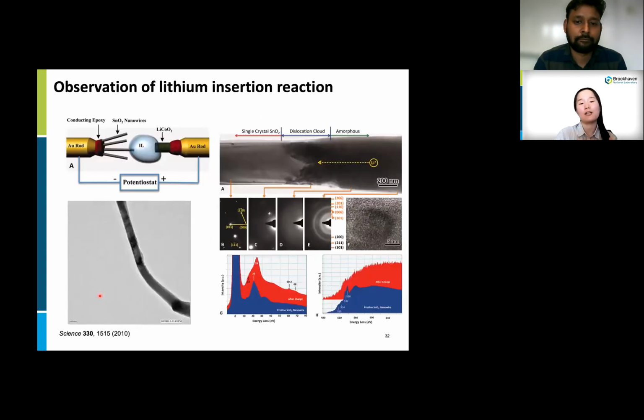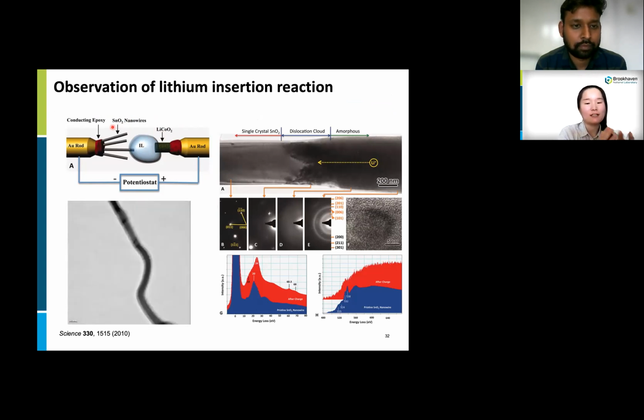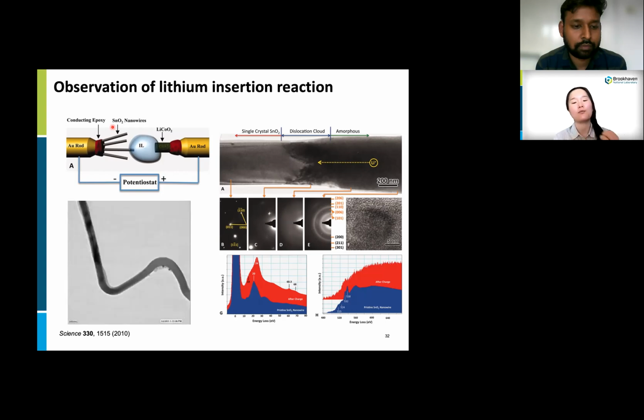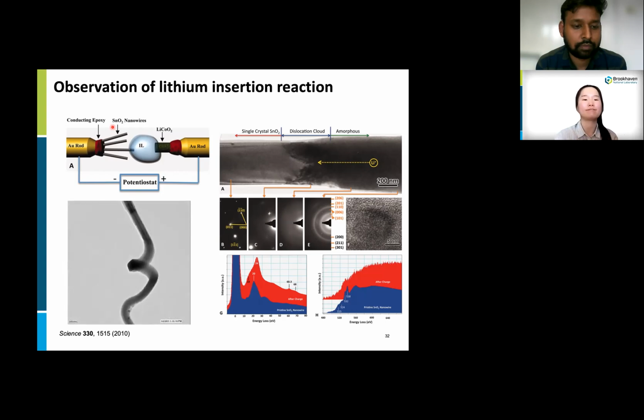An open cell configuration shown here has successfully mimicked battery systems inside transmission electron microscopes. Lithium cobalt oxide is the cathode, tin oxide nanowires are the anode, and ionic liquids serve as the electrolyte. And as lithium ions move from lithium cobalt oxide to tin oxide nanowires, we can clearly see how this nanowire is changed with lithium ions.